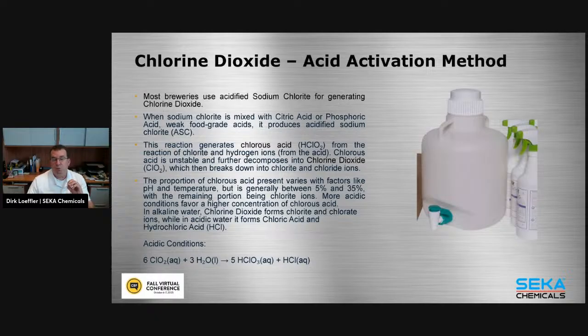Now, there are ways to produce almost 99.9% pure chlorine dioxide, which is better, because you don't have all the chloride attacks breaking down your passive layer. But even those will break down into chlorides afterwards, because chlorine dioxide is also not a very stable chemical. So while you're taking out of the equation the majority of the residual chloride ions, you do have the chlorides that are produced from the chlorine dioxide itself. So those are available. We actually carry those,